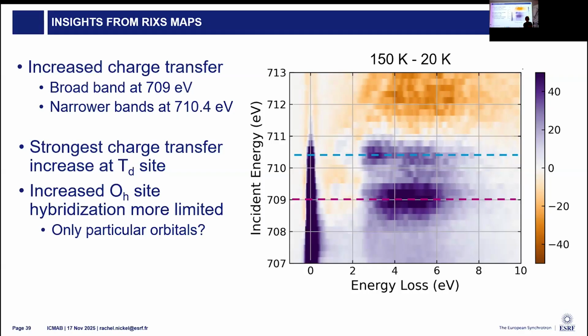So at Diamond, they have much, much better flux at low energies. So if you were in the market of doing, say, an oxygen edge experiment, I would absolutely send you their direction and not ours. Time matters for RIXS because it's photon hungry. And so the difference between our beamline, where it might take 6 hours, and theirs, where it would take 4 hours to get a spectrum, really makes a huge difference.